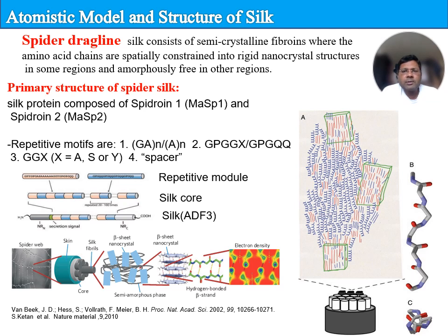Its primary structure, the amino acid sequence, has been optimized over millions of years of biological evolution. Spider dragline silk is thought to be composed of mainly two proteins, spidroin 1 and spidroin 2. These proteins can be described in the simplest picture as block copolymers with polyalanine blocks that consist of approximately 8 monomers, and glycine-rich domains with GGX as the most abundant motif.